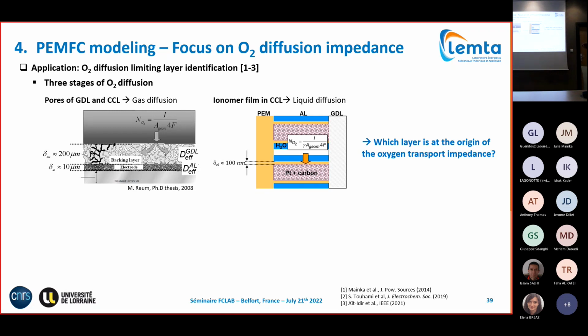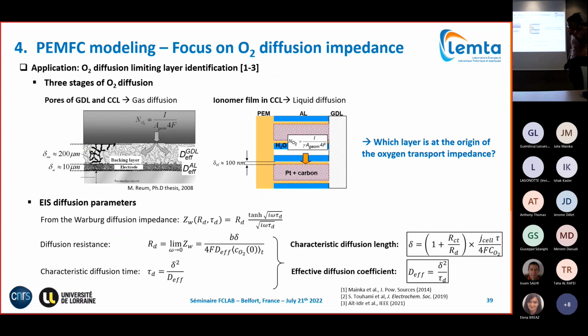Here's a representation using an agglomerate model, and here it is liquid diffusion when your oxygen is dissolved in the ionomer. So 3 different stages having different characteristic diffusion lengths and different effective diffusion coefficients. So the question is, our low frequency loop, the diffusion impedance measured, which layer is it linked to? And we try to analyze to answer this question. So the idea is to fit our curves with our TLM and Randles model, identify our diffusion parameters, so the diffusion resistance and the characteristic diffusion time.